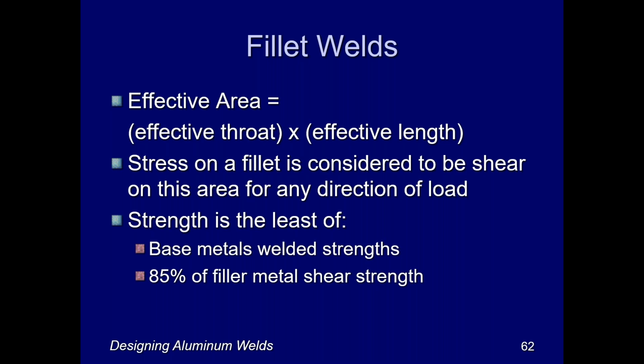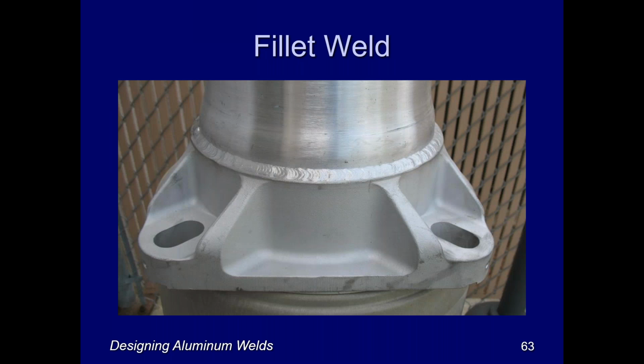And that's a conservative assumption because the shear strength is less than the tensile strength. And the strength then is going to be the least of the base metal welded strengths and 85% of the filler metal shear strength. That 85% factor is the knockdown factor for fillet welds. And that's because fillet welds represent a disruption in the stress flow through a part. They represent stress risers both at the beginning and at the end of the weld as you're going down the length of the weld. And then cross-sectionally, they represent an abrupt transition between the weld metal and the base metal. And therefore, that 15% knockdown, in other words, applying a 0.85 factor, is designed to take that into account.